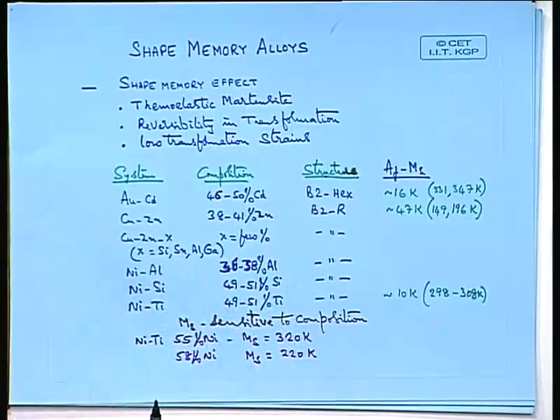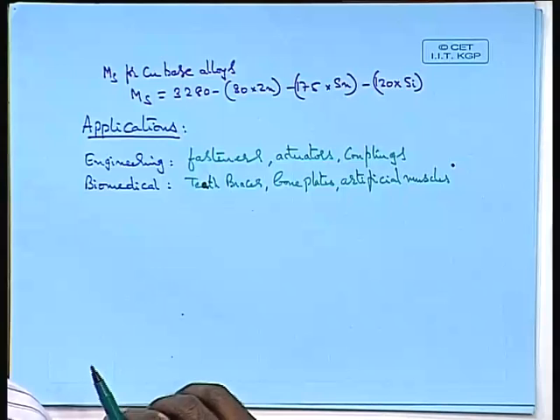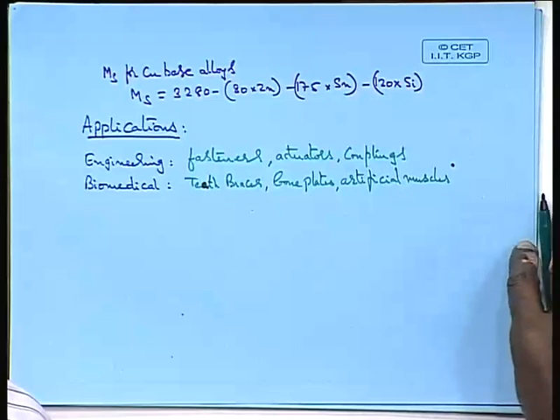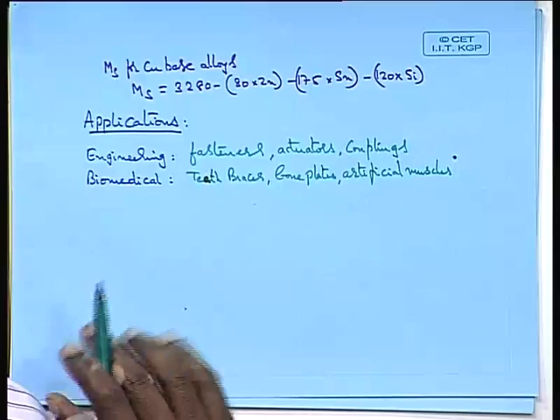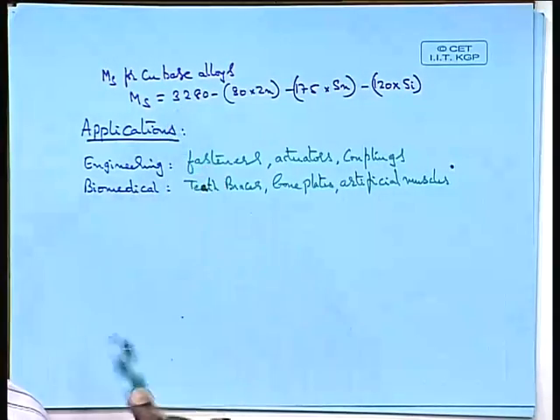So there are a number of these alloys, and what is important to note is that in most of these alloys, the shape memory effect is observed at intermetallic compositions. Most of these phases which undergo martensitic transformation and give you the shape memory effect are mostly intermetallics and ordered intermetallics. And these ordered intermetallics will undergo these thermoelastic martensitic transformations, which will give you this kind of shape memory effect. And this MS temperature, as I told you, is a function of composition in many of the alloys. If you look at the copper zinc based alloys, the MS temperature is a strong function of the composition, as is shown here. MS is given by 3280 minus 80 into zinc minus 175 into tin and minus 20 into silicon.